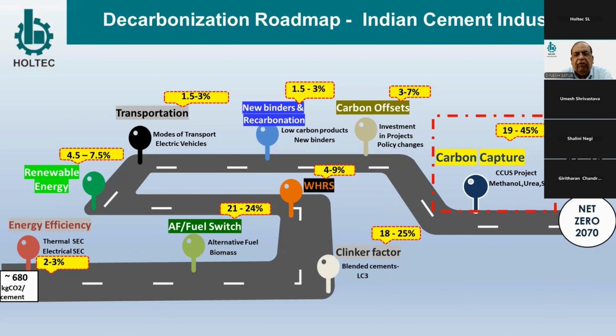Now we go to the decarbonization roadmap. This is with respect to the Indian cement industry. We are currently at an average of say 680 kg CO2 per tonne of cement, on a 2020 basis, and our target is to reach net zero by 2070. So what are the various potential areas and how much potential is there? That is depicted in this chart. About 2 to 3% in thermal and electrical energy reduction we could achieve. AF fuel switch, alternate fuel, biomass, etc., 21 to 24%. Then clinker factor reduction, converting to blended cement, LC3, etc., 18 to 25%,